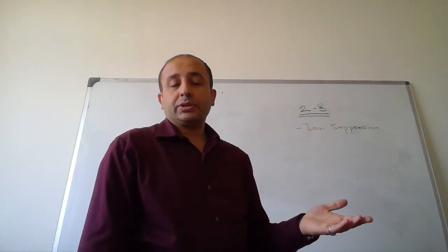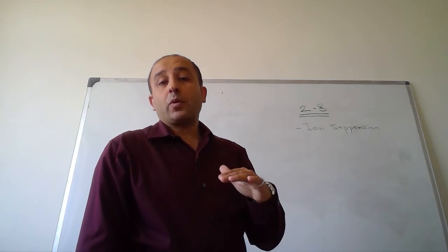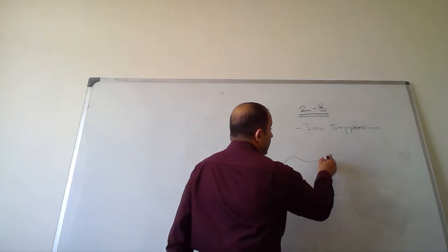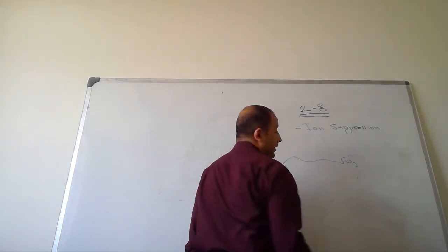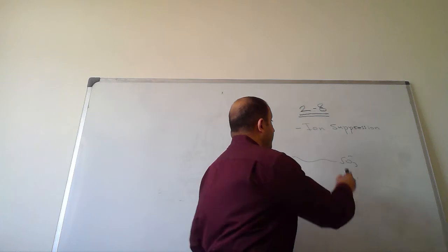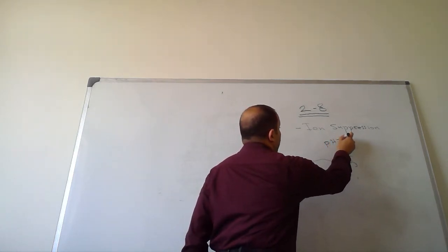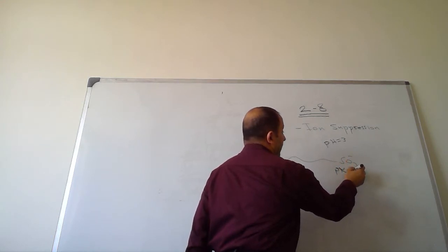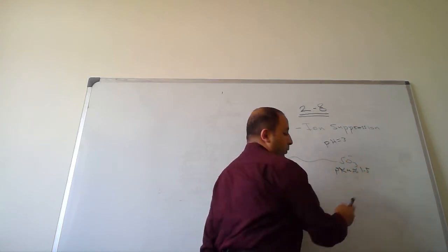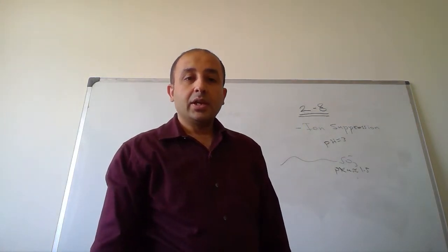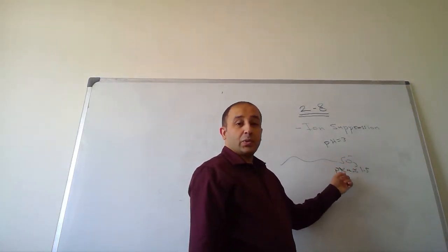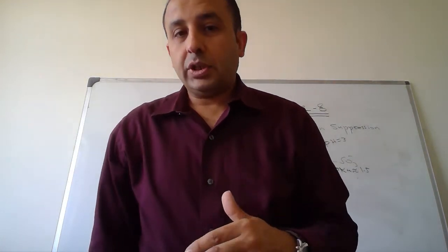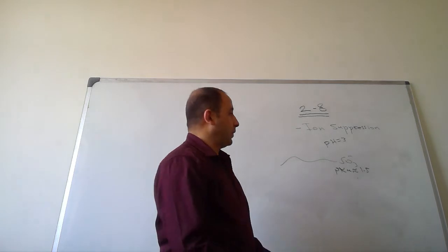So we use ion suppression sometimes with an ion pairing agent. The good thing is that in an ion pairing agent, sulfonate cannot be suppressed by pH 3. The reason is that the pKa of sulfonate is around 1.5 or 1.2, something like this. So these acidic groups need pH below 1 in order to be in unionized form.